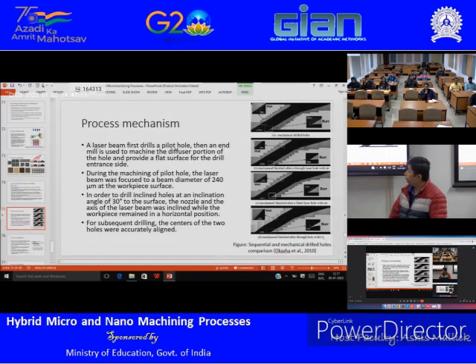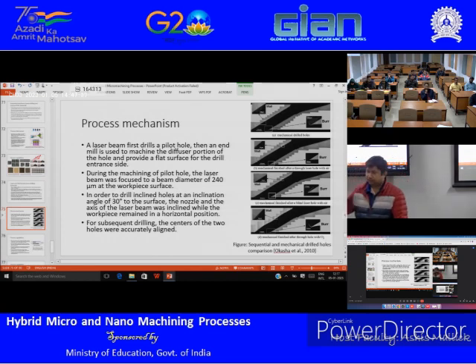So here you see that, first, if you just do the mechanical hole, the first one is good, but it has some burr formation, because as I mentioned, first of all, this process is not very good for difficult to cut material, because mechanical drilling is not good for difficult to cut material. So they are using comparatively easier to machine material, but mechanical drilling can end up getting lots of burrs. So that's what it says.